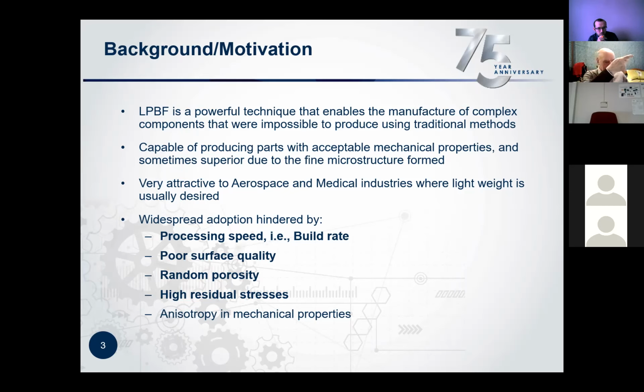And of course, the surface finish is also a factor, especially if you're looking at aerospace components where fatigue strength is really an important parameter. The surface quality requirement there is usually below 1 micron, which we are not able to get with additive manufacturing unless you apply some post-processing finishing on it. Of course, random porosity is another issue, and porosity can affect your mechanical properties.